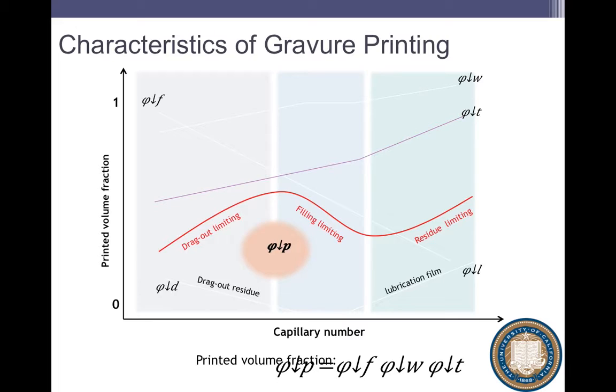So there's a region that is perfect, or as good as it's going to get anyway, and that turns out to be right over here. And it turns out it's universal. We've tested it for hundreds of inks on hundreds of substrates at hundreds of print speeds and viscosities, and we always get that curve, and that universal point is always the same. So that now gives us a design rule when we are trying to scale gravure from tens of microns to single micron or submicron. All we do is we design our processes to hit that point.